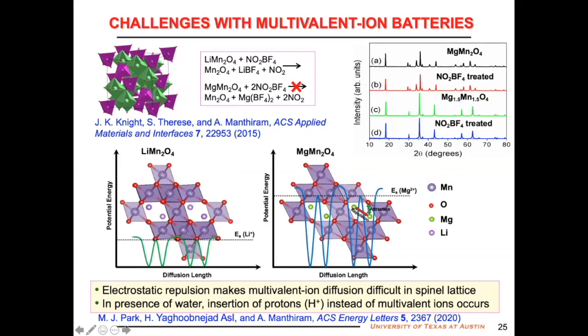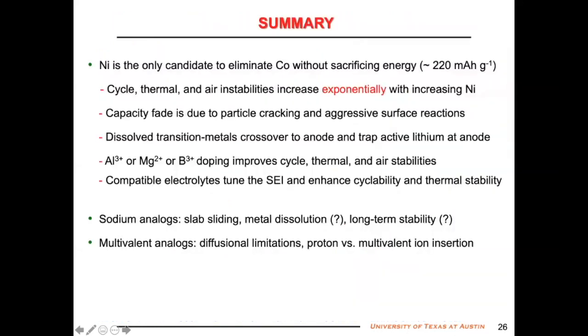So in close-packed structures, diffusion will be a problem. Also, in these materials, if you have a trace amount of water, proton may be inserting in these materials rather than multivalent ion. So one needs to be careful to employ a series of different characterization techniques to have a good understanding of whether it is really proton or multivalent ion. If you go to more covalent systems like sulfide, then you have better possibility, but then the voltage will decrease.